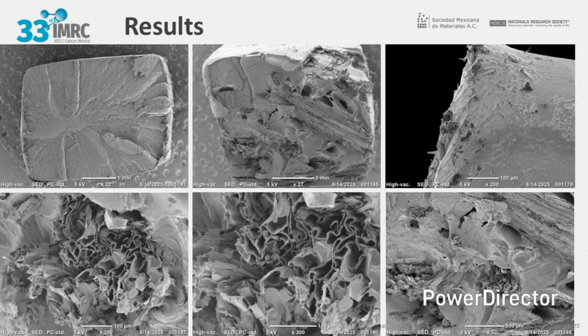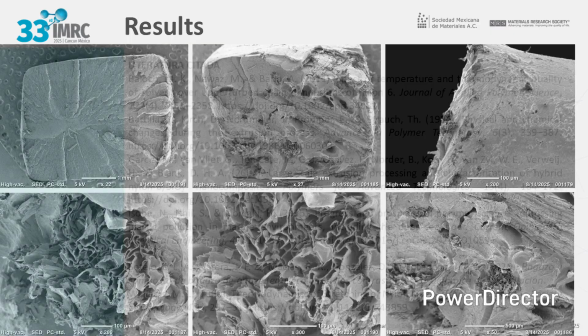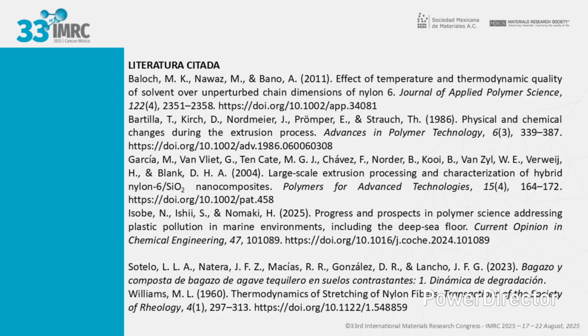Likewise, torn fibers with relatively clean surfaces are identified, reinforcing the hypothesis of insufficient interfacial adhesion. However, in some sections, partial coverage of the fiber by the polyamide is evident, indicating a certain degree of mechanical anchoring. And this is the bibliography.